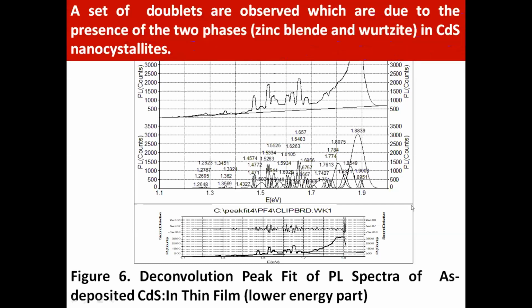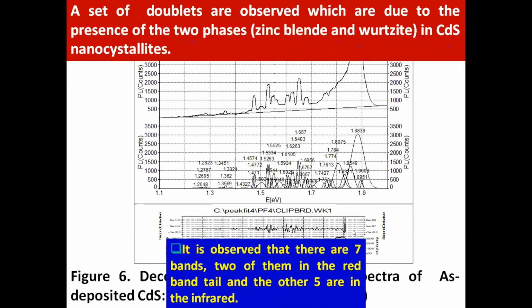Now, this fit shows bands, and we have 7 bands. The peaks are collected in bands, and the number of these bands is 7. 2 of them are in the tail of the red band, and 5 of them in the infrared region. The strongest one is this one, and it is in the range 1.82 to 1.9 electron volt. It contains 5 peaks and 1 doublet.